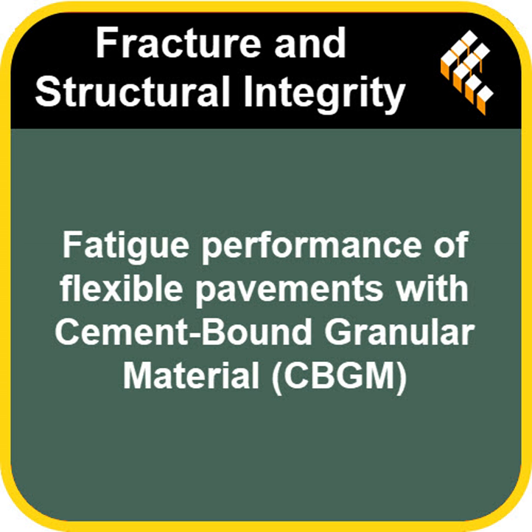It considers the tensile strain, how much the material stretches, and compares it to a specific failure strain limit, which was 125 microstrain in this case, a very small amount of stretch. It also includes a factor for shrinkage-induced cracking. Okay, so we have Dempsey, very conservative, predicting early failure, and De Beer, field-calibrated, predicting much longer life. Two different models, two ways of looking at the same problem. How did the study actually apply these to a real-world type scenario?